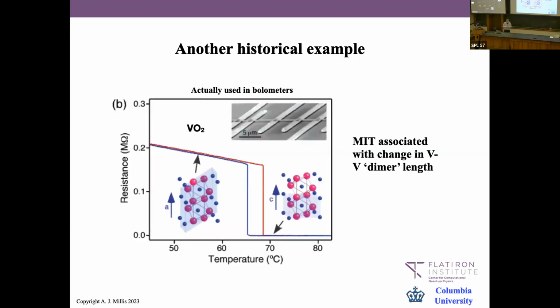Here's another example, vanadium dioxide, which I'm told is actually used in commercial bolometers. It has a very sharp metal to insulator transition at a temperature a little bit above room temperature. And apparently it's commercially viable to put the average temperature right here. The resistance versus temperature is so steep that a tiny amount of absorbed infrared radiation changes the temperature enough to make a measurable change in the resistivity. Right? So it's night vision, basically.